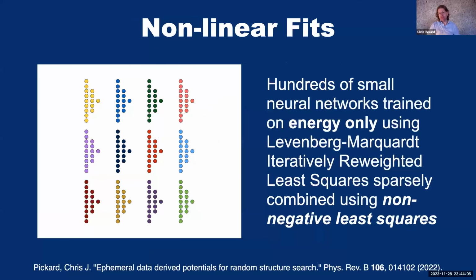And then when it comes to the nonlinear fits, we use neural networks. There are other fits you can use, but actually neural networks are extremely powerful. We only train on the total energy of the system. This simplifies the approach, and because we have small diverse unit cells, we're still able to learn effectively what the forces are between the atoms, but only through the energy. We do the training of the neural networks using the Levenberg-Marquardt algorithm, which is extremely fast and accurate for modest sized neural networks. It doesn't work for very large networks because it has essentially a matrix inversion in the number of parameters of the neural network at some stage. So there's a limitation to how large networks you can look at, but we actually only look at very small neural networks, typically only with 1 layer and 5 hidden neurons.